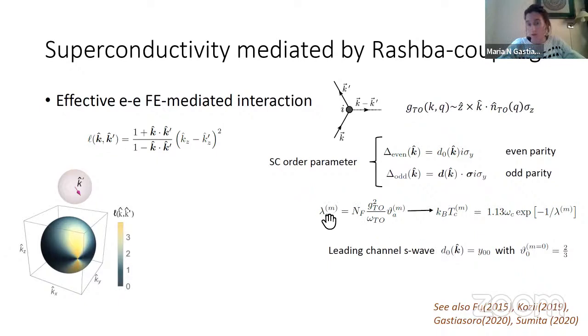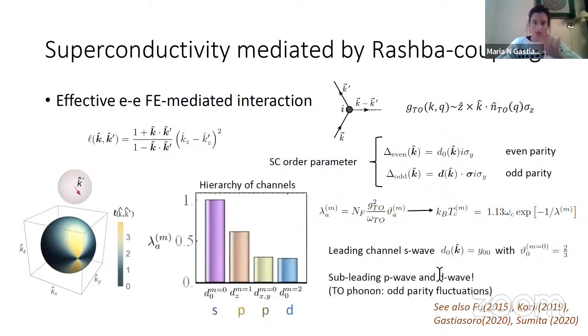And once you have that eigenvalue, the eigenvalue will be as usual. We are solving the weak coupling problem. So this is some density of states times some pairing interaction that will have the information of your phonon, so the bare coupling and the frequency. And then with that, you know that TC will be proportional to the usual BCS kind of expression. And the highest lambda will be, in principle, the state that the system will condense into. So the leading channel for this mechanism that we find is the S wave, or the A1 irreducible representation, and the maybe more unconventional or special characteristic of this pairing mechanism is